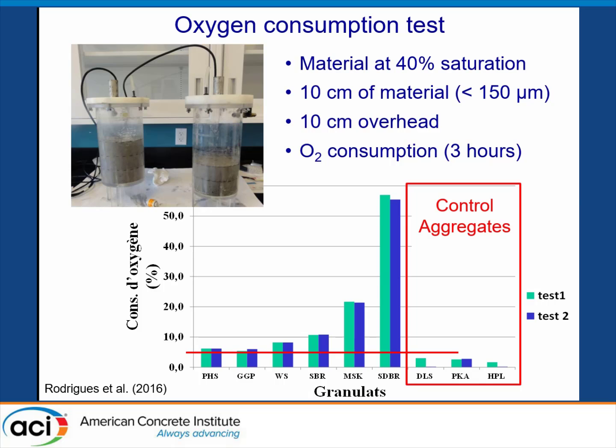I will just show you a few results here. We have this control aggregate without sulfide. It doesn't really consume oxygen. This is the aggregate from Trois-Rivières. This is a very rich pyrrhotite type aggregate, and different other materials containing sulfide-bearing aggregate.